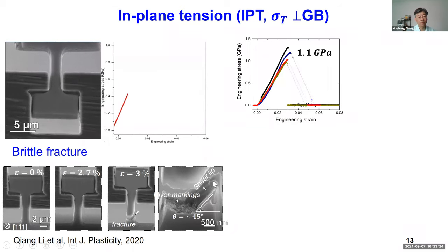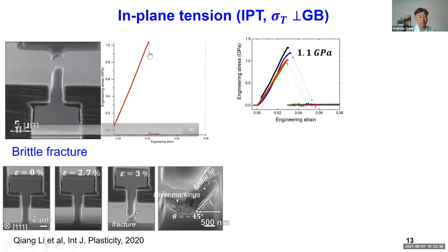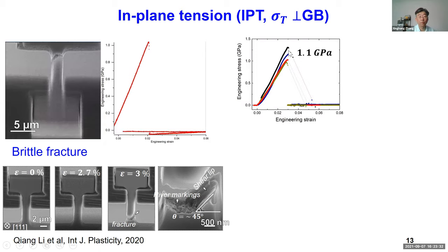If you pull on it, you see this linear elastic behavior, boom, and the entire sample fractures. So it's pretty brittle. You reach a stress level close to one GPa, then you don't see much plasticity. Just very brittle behavior. And you see some shear lips surrounding the gauge section, but in general, it's a brittle fracture behavior.